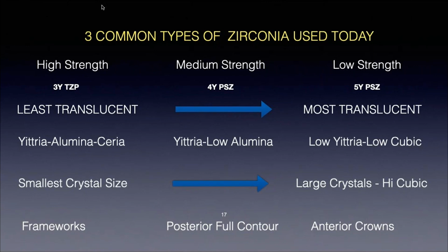And the low strength is the 5Y zirconia, and that's the most translucent. It has a very, very high cubic content, which is larger crystals. And you can only use them on anterior crowns. And those are the ones that are susceptible to too much air abrasion. They can really weaken the strength.